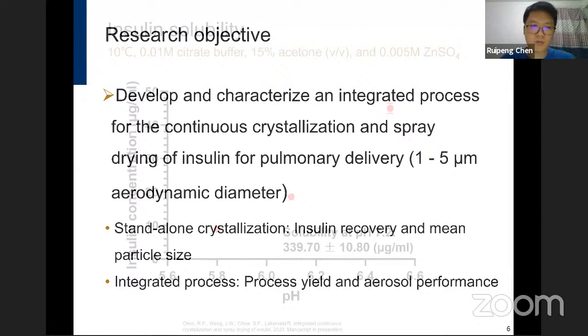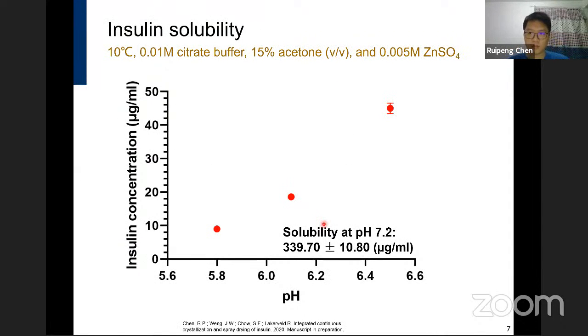Okay, so let's first begin with the solubility data, which is measured for the typical crystallization range for insulin, in the pH range of 5.8 to 7.2. As we can see in this figure, there's a huge difference in the insulin solubility at different pHs. So this suggests high supersaturation can be generated if we apply a pH shift in a tubular reactor.